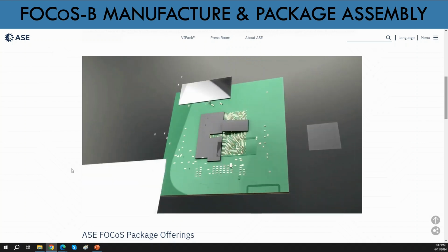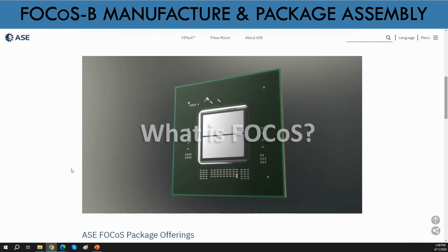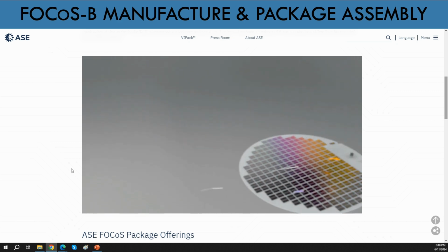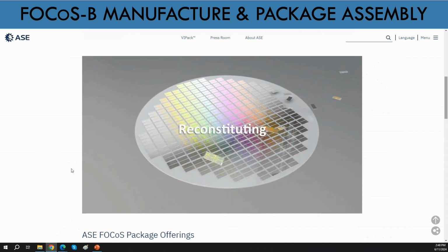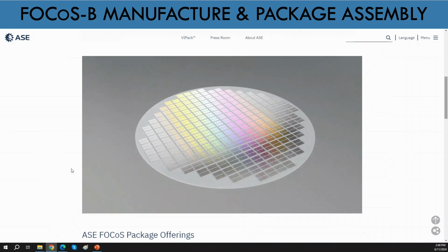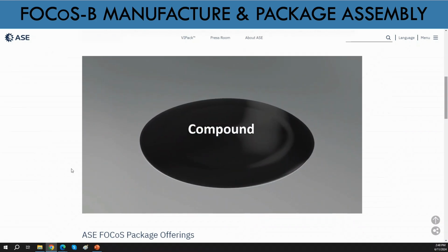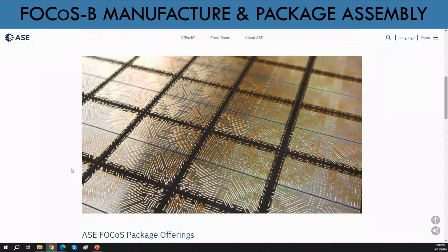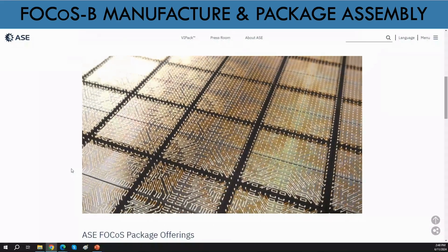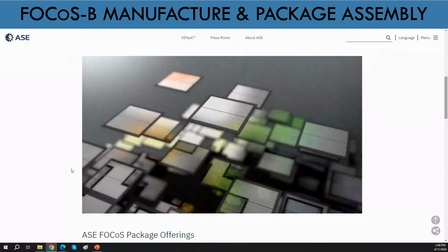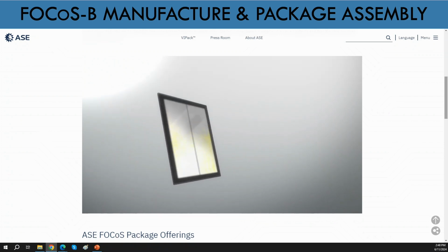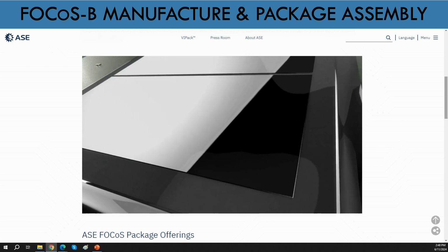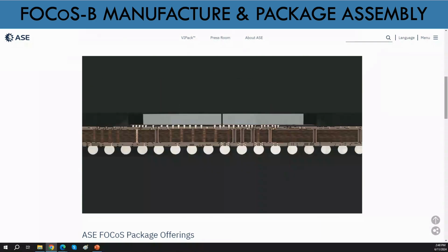The biggest advantage of fan-out packages is to achieve homogeneous and heterogeneous chip integration. 2 chips from different wafers are attached onto a carrier wafer based on the designed functional partitioning. After molding encapsulation, the reconstituted wafer is formed. With wafer staying face-up, wafer-level redistribution layer and C4 bump process continues for intra and inter-chip across this reconstituted wafer. After the fan-out chip is flipped onto the substrate with reflow, the assembly of a fan-out chip on substrate is done.